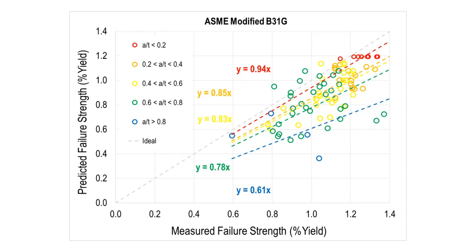We actually have a nice rainbow almost of data points there. Very interesting to think about. This has, I'll say, some quite significant ramifications on how pipelines are being managed these days in terms of corrosion assessments. We see from these two plots that if we have shallower and shorter flaws, we're going to tend to have fairly accurate predictions. But as we go to longer and deeper flaws, we become increasingly conservative.